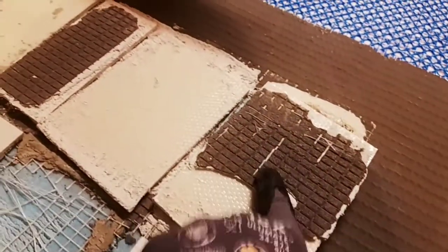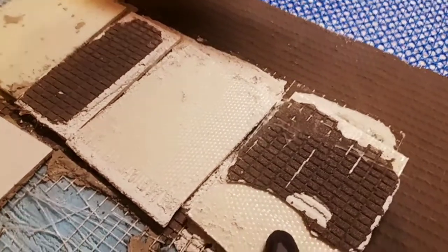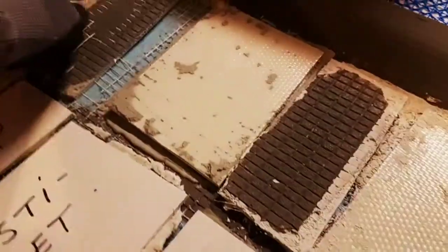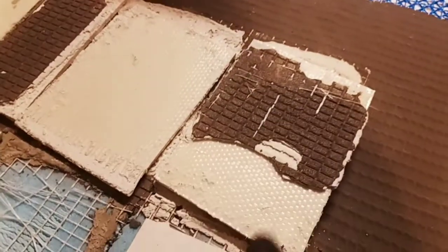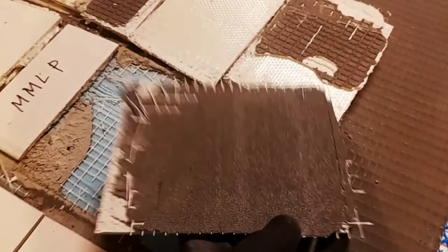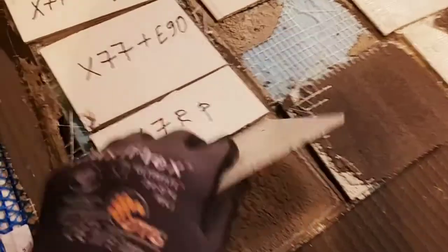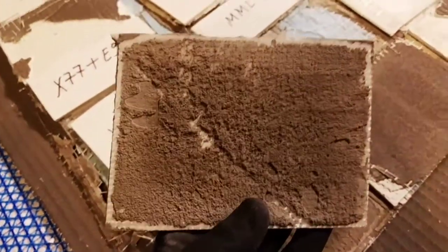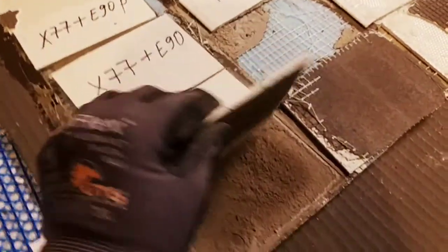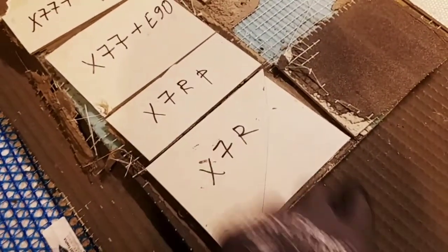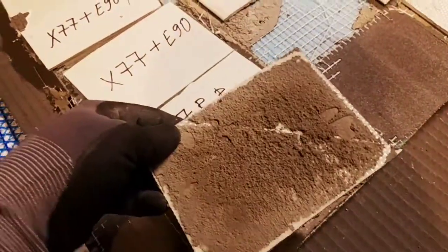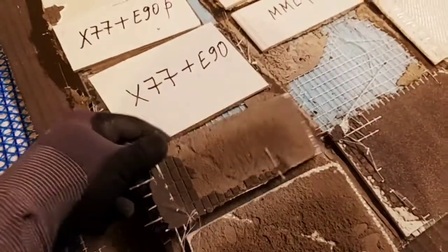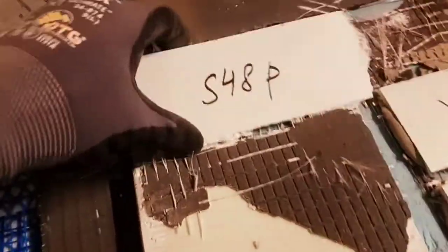X5, I was kind of surprised that actually X5 showed better adhesion to resin backing than X32 and X78 and X90. I was very surprised, but still, this is not a perfect adhesion, of course, but X5 with P4. X7R, it is important to say that, you see, this is the adhesion to resin backing directly, but the bond was somewhat poor. I was able to easily remove this piece. X7R with P4, X77 plus E90 with P4, S48 with P4.